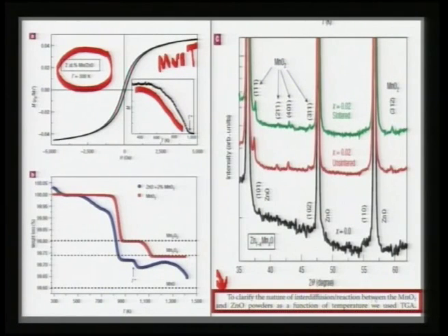What this group did was take zinc oxide plus 2% MnO2, mix them together, and do a TGA analysis to clarify the nature of inter-diffusion reactions between MnO2 and zinc oxide powders as a function of temperature. Thermogravimetric analysis is not a very costly instrument — it is affordable and almost every lab or analytical center would have it. But look at the way this group resorted to a simple technique, not much involved, to elucidate some primary features out of it.